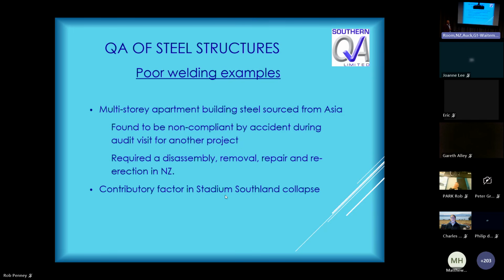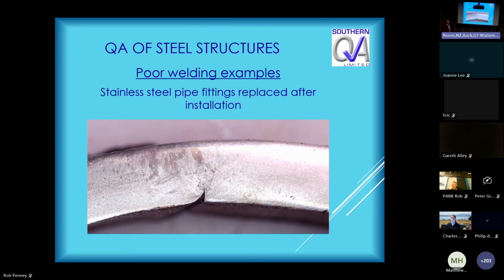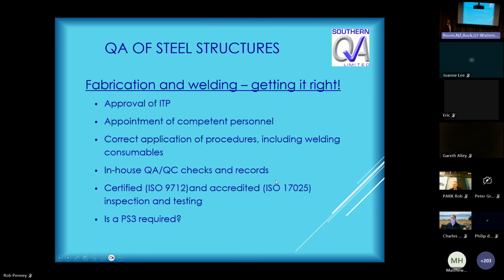Poor welding was certainly a contributing factor in the Southland Stadium collapse that we saw a photo of before. Here's a stainless steel pipe fitting. There's a whole bunch of them had to be cut out and replaced after installation because they had this type of defect in them. The lack of root fusion. So the weld bead has wandered off, hasn't fused one edge of the root. Not ideal.